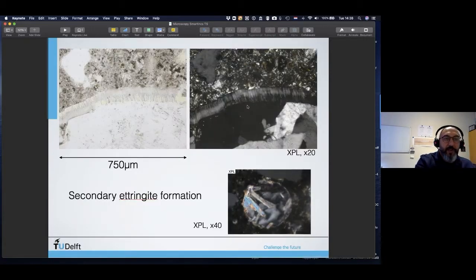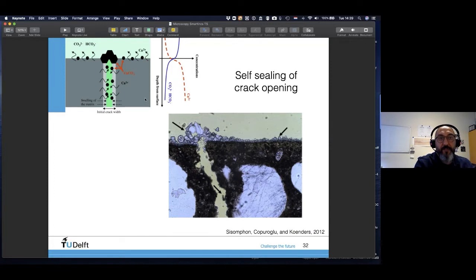Okay, ettringite is another secondary formation you typically see in concrete as the delayed ettringite formation, secondary ettringite formation, and so on and so forth. You see they are needle-like and can form in any place they can find, basically. You see them generally at the interfacial transition zone because you have relatively more capillary porosity there compared to the bulk. But where I'm trying to get at is actually observing self-healing with these techniques.